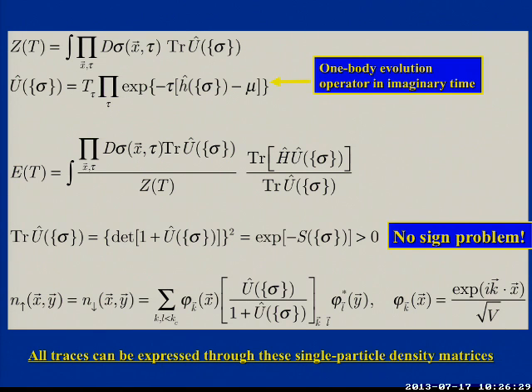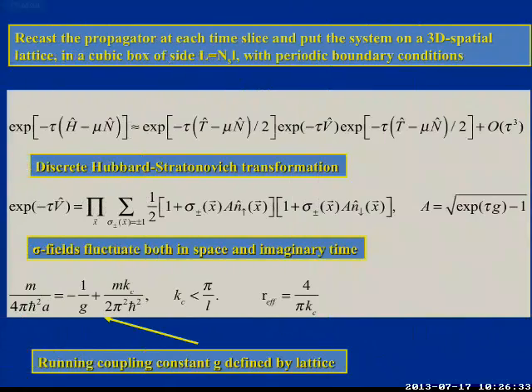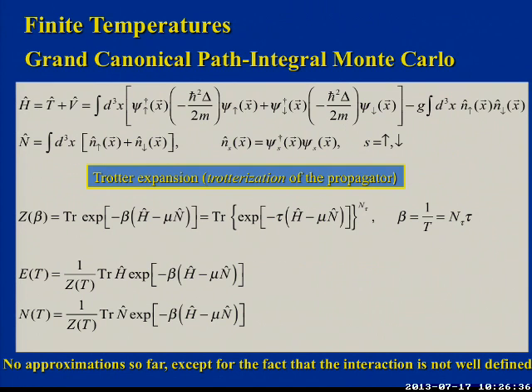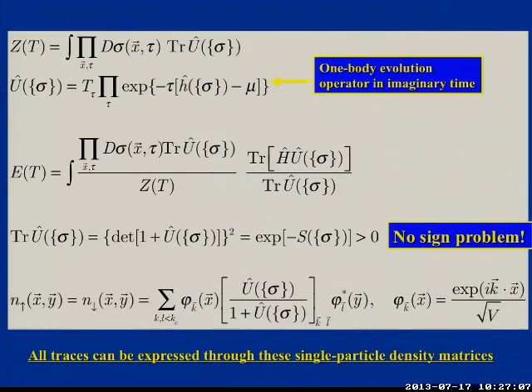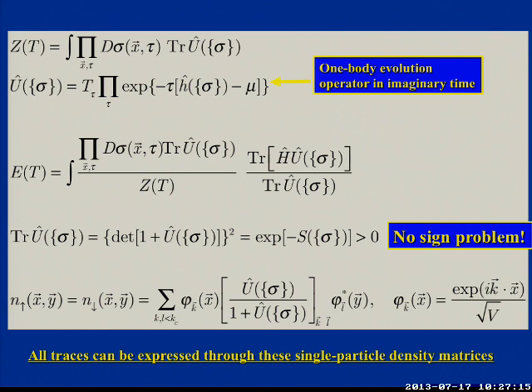Now, once you do that, I skipped a formula here. If you want to see, I can do it quickly, derived, but I think I skipped it. I have the interaction. This is a two-body interaction. What I do, I apply the usual Hubbard-Stratonovich transformation. The coefficient here is negative, so there is no problem. But actually, we do a little bit better than that. We do discrete transformation, which goes back to Hirsch, I believe. It's discrete in this case because this is on-site interaction. You need only one stochastic field. So it's a discrete stochastic field. And this is our stochastic field, which obviously, remember that I have a running time, imaginary time. I have a lattice point, so the stochastic field depends on those four coordinates.